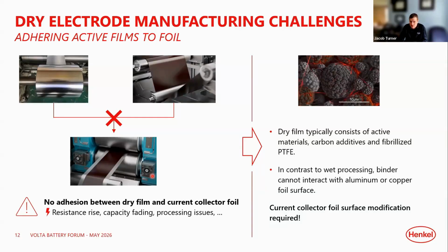The reason that these typically don't stick is that a lot of these freestanding films just consist of active materials, carbon additives, and very small amounts of fibrillized binders, typically fluorinated ones like a PTFE. So in contrast to wet processing, where there's a natural interface formation due to the liquid penetrating the surface roughness, these freestanding films don't have that ability. So it requires some sort of modification to help enable this technology. One of which is these conductive coatings to modify that current collector or foil surface.